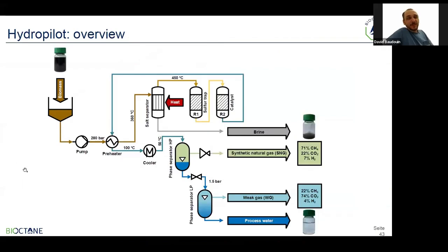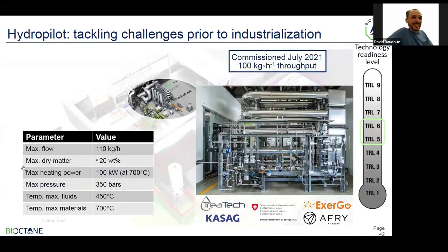And this is a view of the pilot plant unit that was commissioned a few years ago, and this one can operate at 100 kilograms per hour. The catalyst bed on this platform is about 20 kilograms. So it's much bigger than the smaller scale one, which is about half a kilo.